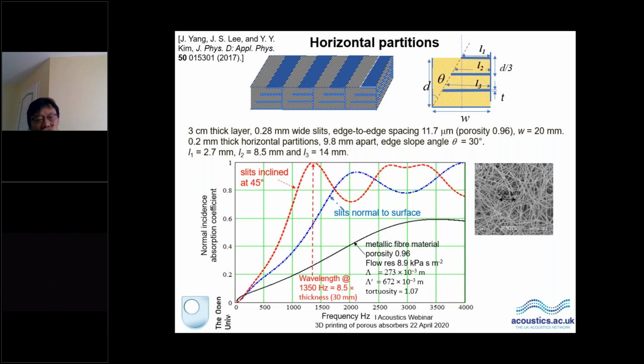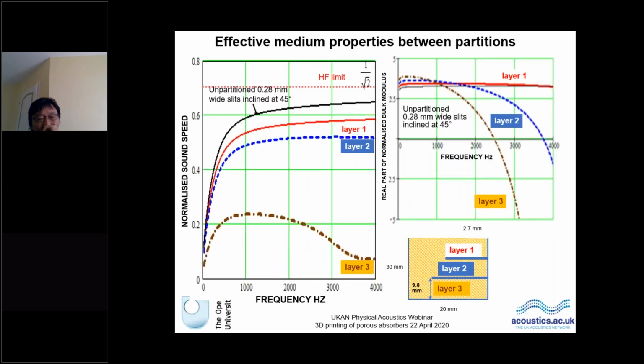And what is interesting about these horizontal partitions is they also predict the possibility of some kind of metamaterial behavior in the lower layer. This is shown in these plots here, where you can see that the frequency dependence of the so-called equivalent fluid normalized sound speed in each of these layers has quite different behavior in terms of the lower layer. And also, if you plot the real part of the equivalent fluid bulk modulus for this partition system, then in the lower layer it's becoming negative, which is one of the things that happens for metamaterial behavior. I think this is attributed in the papers to some kind of resonance, that these horizontal partitions are creating side branch resonances, I suppose, not that dissimilar to the dead end pore structures that Philippe was talking about.